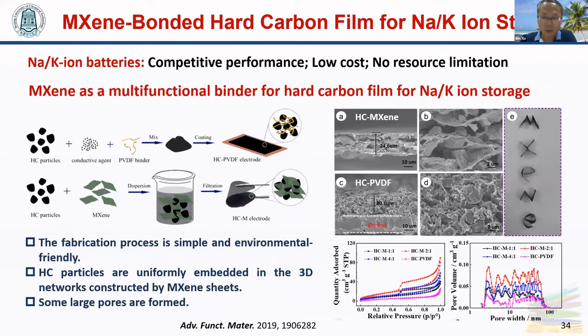MXene binder can also be used for carbon electrodes for sodium and potassium ion batteries. We know that hard carbon is a good material for sodium and potassium ion batteries. However, as sodium and potassium have a larger ion size than lithium ions, the cycle performance of hard carbon is not very satisfactory due to the large volume change during charge-discharge. Using MXene as a binder, we can solve this problem. The fabrication process is very simple. We only vacuum filter the mixture of MXene and hard carbons.